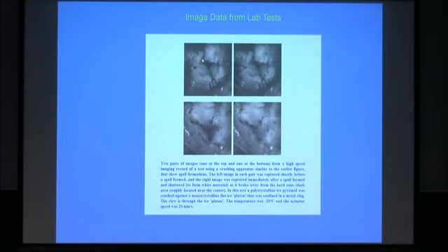So again, these are before and after spalling events. This is a hard zone, and a piece of the hard zone has shattered. And this is the crushed ice around the sides. This was another event in the test. This was a large hard zone, and a big piece of that shattered. So you see this same kind of physics happening when ice is crushing against ice, and this is really important for ice crushing within glaciers, but also for ice floes that are rubbing against each other, sliding, banging into one another. Same kind of physics is happening.